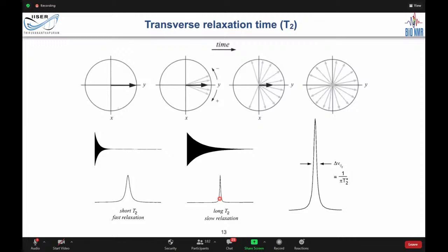If you have a long T2, you will have sharper lines. That is for most small molecules. But if you have proteins and all, you have short T2. That means it relaxes much faster, that it dephases much faster. You have a broad signal. You can also see this from the FID itself. You see a fast decay, that means faster relaxation. You have slow decay, slow relaxation.